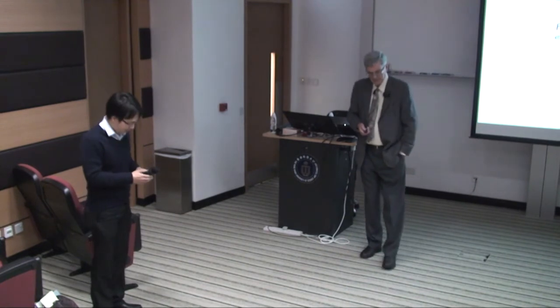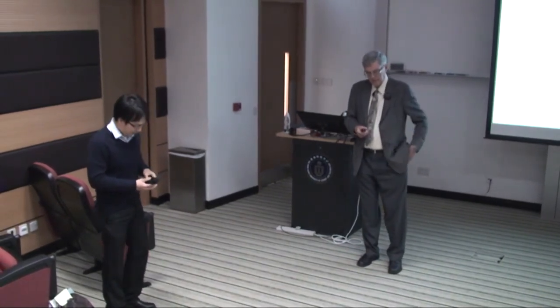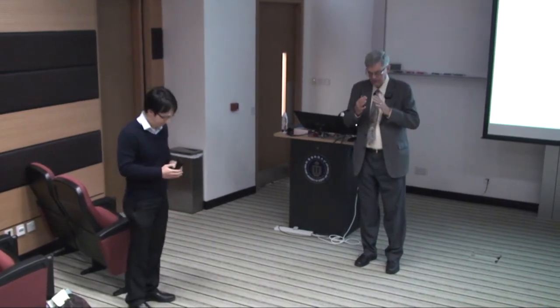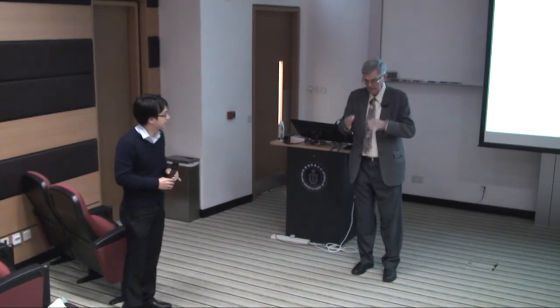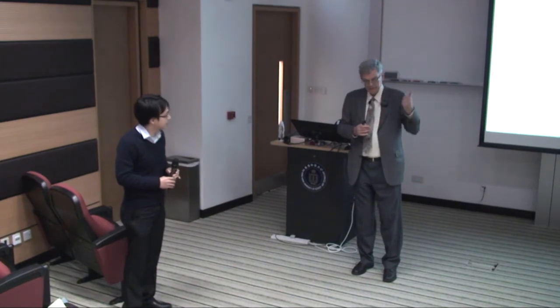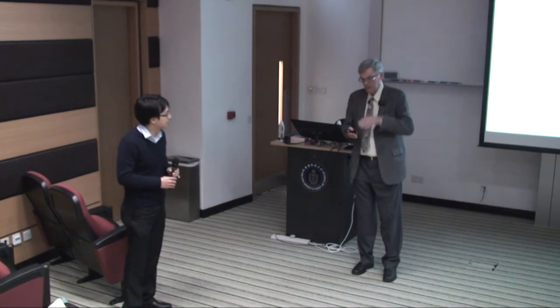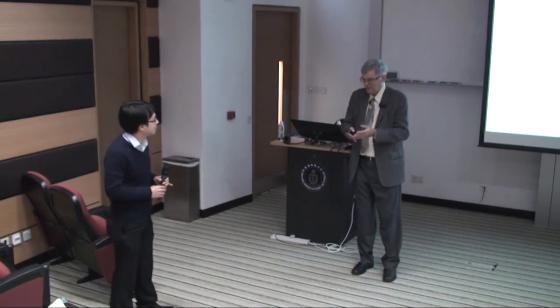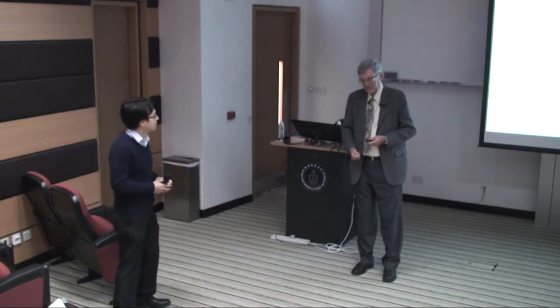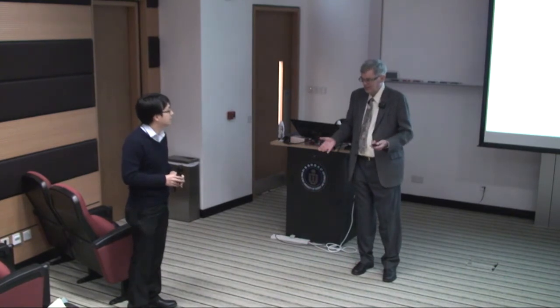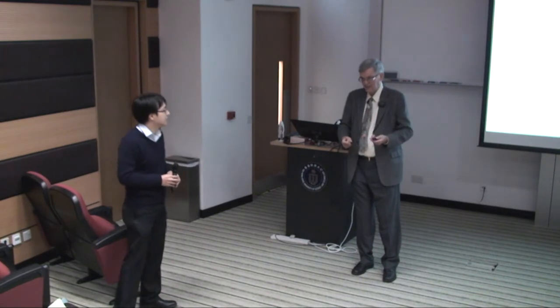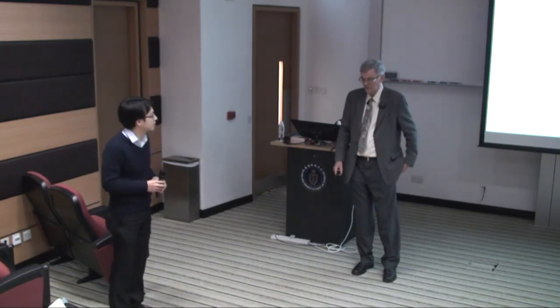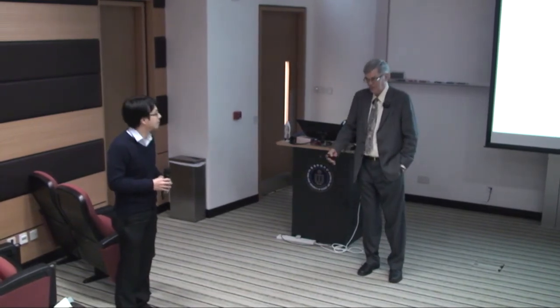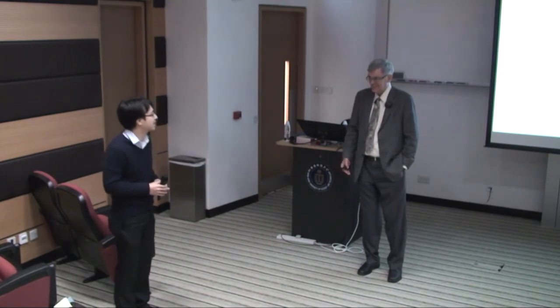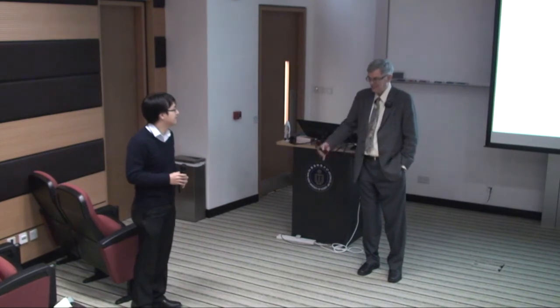Well, I think you run into the same problem. The D8 state in nickel is a spin 1 state, and it has a very good cubic octahedra. Now, I said that in the cuprates, the octahedra is elongated. So in nickel oxide, which is D8, you have this very beautiful cubic octahedra. If you put in an extra electron or you take out an electron, you've changed the local symmetry, and the lattice around it relaxes, and you get self-trapping of what's called a small polaron. So nobody has found any superconductivity or even metallic conductivity in the nickelates. There were some speculations about it, but it never went anywhere.